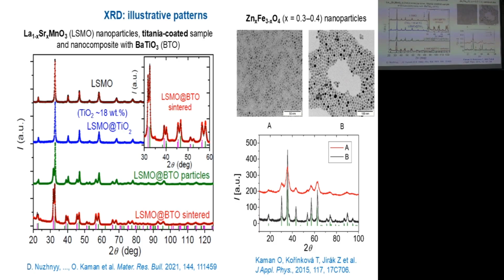You see just the pattern from the first case, and there is nothing more. So you can see that the amorphous admixtures are typically not manifested if the content of the amorphous phase is not huge. If the content is large, you can see some additional very broad peak, which has no sense for some analysis. But it can also be like this, that you will not see any signature of some amorphous component in the sample.